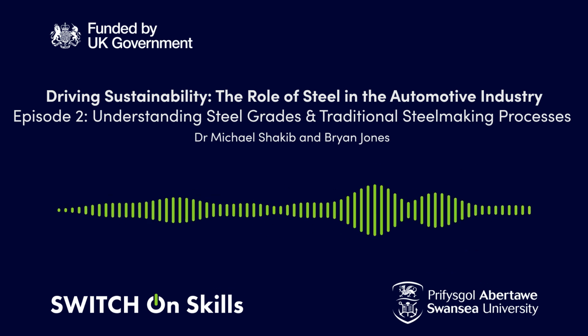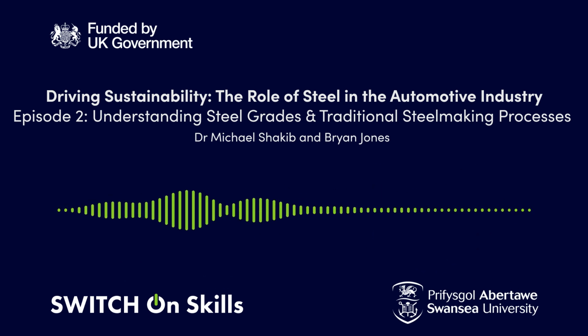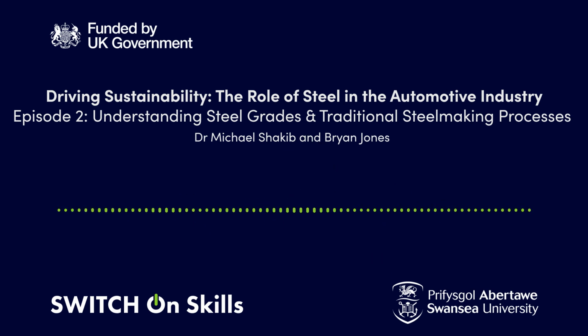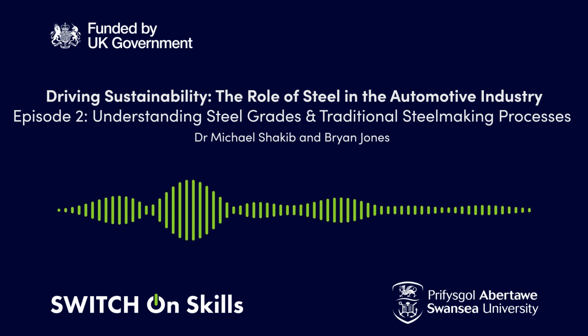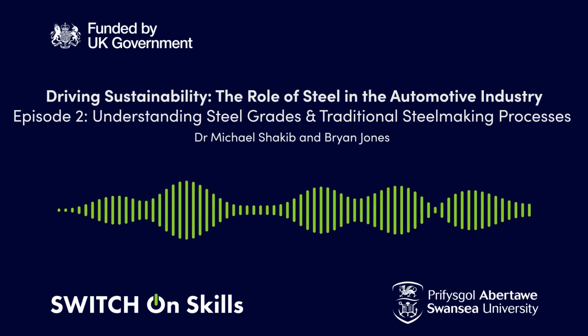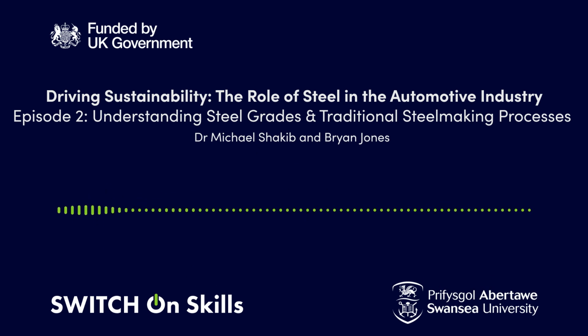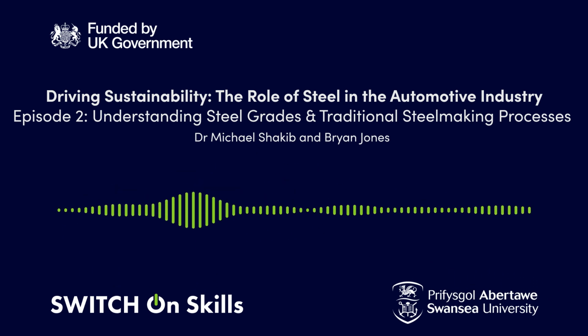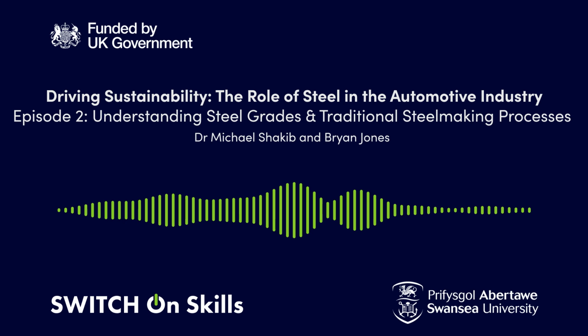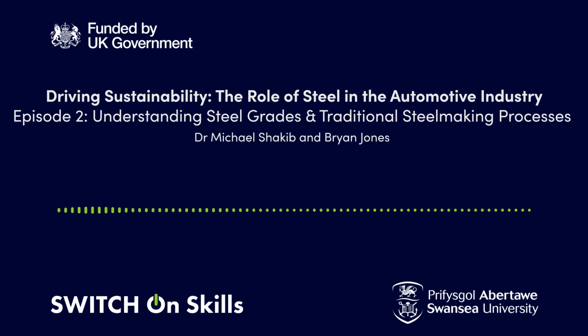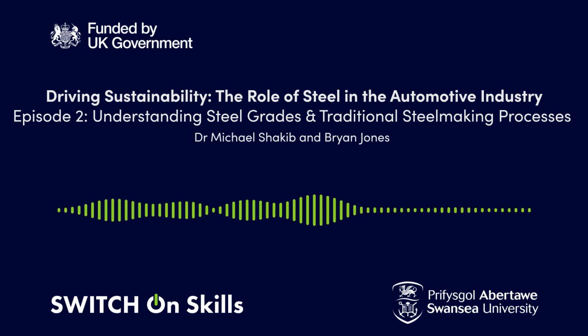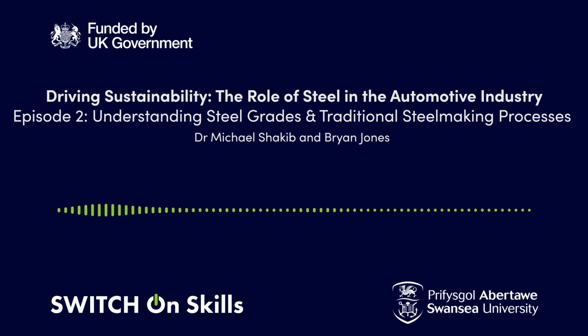Okay. So my next question is, Bryan, can we produce all the grades of steel that we need for automotive applications from the electric arc furnace? Well, that's an open question from what I can see. Fantastic. Because the literature tends to suggest that there are limitations in terms of getting the right chemical composition if, for example, you're making interstitial free steel for packaging or for automotive application. So this is a sort of work in progress, if you like. Because of the cost advantage of making strip steels via the electric arc furnace route, because you're using less energy in converting scrap to steel than in converting iron ore to steel, there's a cost benefit there.